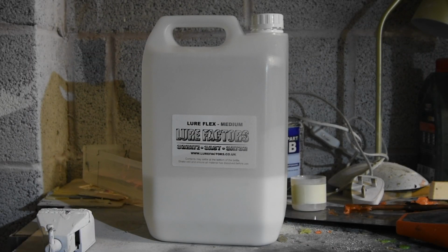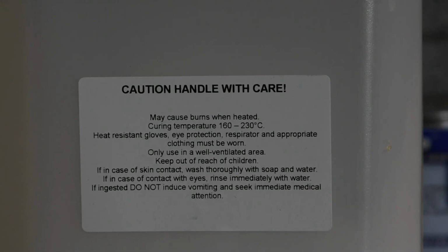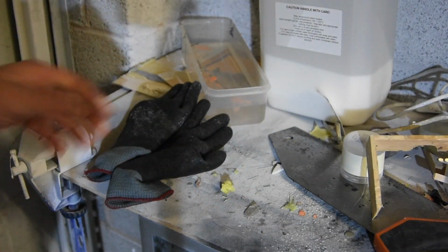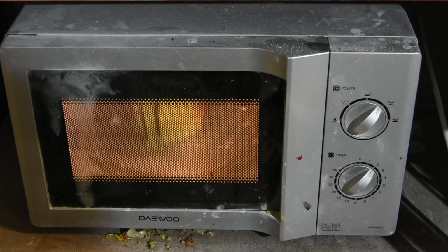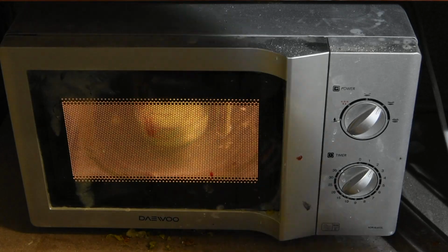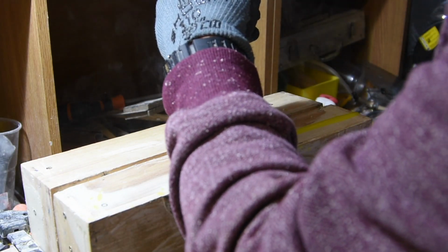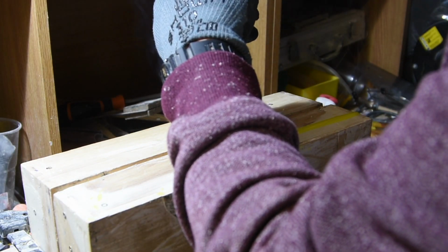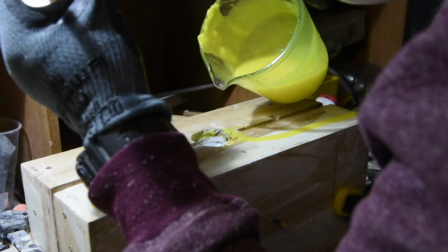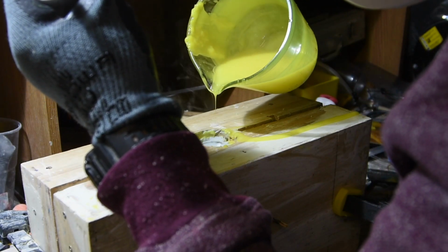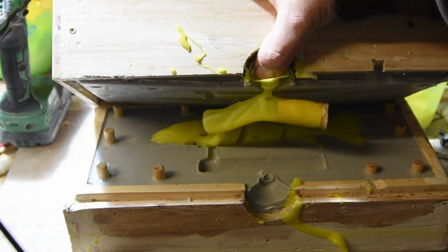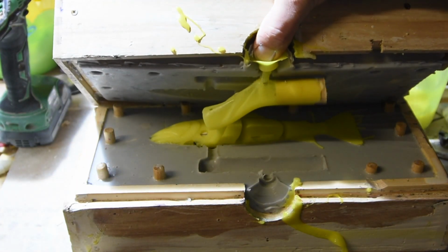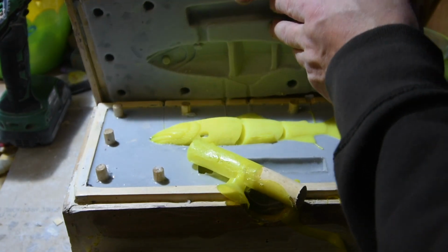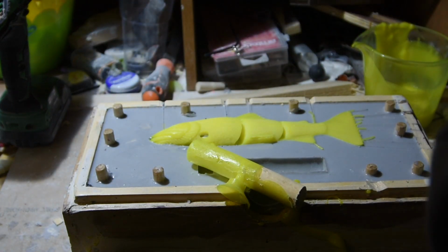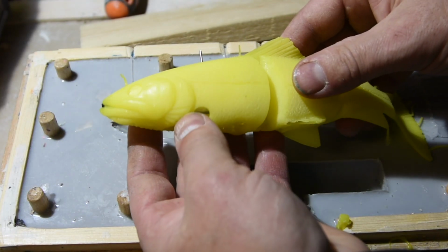Onto the injection moulding. So I clamp the mould together and then heat up my soft plastisol. I heat it to about 170 degrees, 180 degrees, let it cool down to about 165 degrees, and then inject it into the mould. The first attempt was a total disaster. Basically my injector was too small and my expansion chamber was too big.